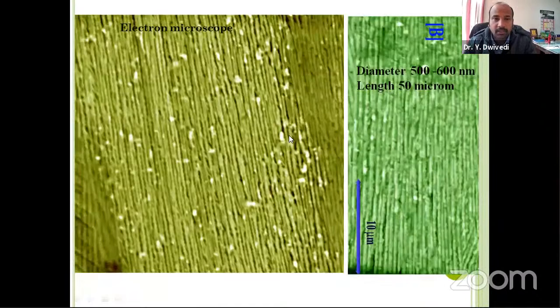From the upper view, with the help of crushed powder, if you see under this electron microscope, you can see these fibers. We have estimated around 50 micron length at least - I mean it is more than that actually, but 50 micron is unbroken, you can say. The diameter is approximately 500 to 600 nanometers.